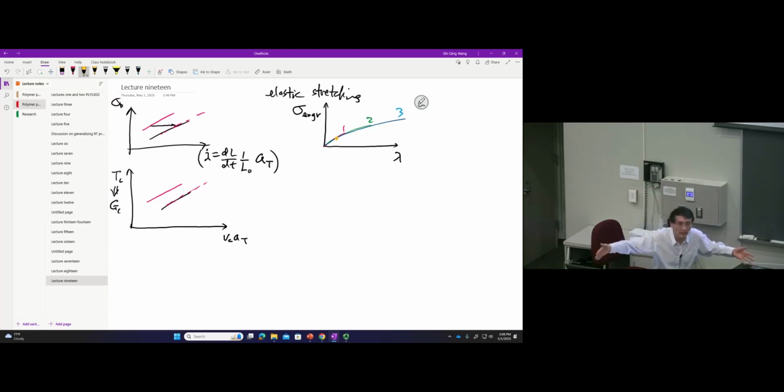Except the breaking is not at the same time, but you hit the same stress up to the point where the first one breaks, which means there's no viscoelasticity. Do you understand that? Meaning it's a purely elastic system. Please don't bring Maxwell because it's purely elastic. If you like to use Maxwell, don't put a dashpot there. Call it the Hookean element, which is what it is.